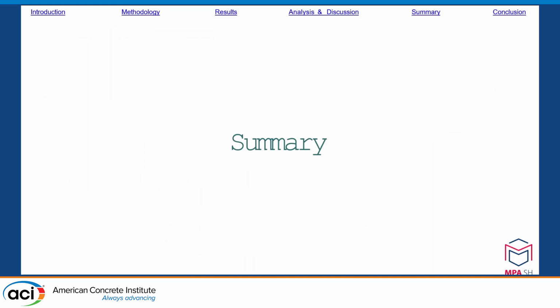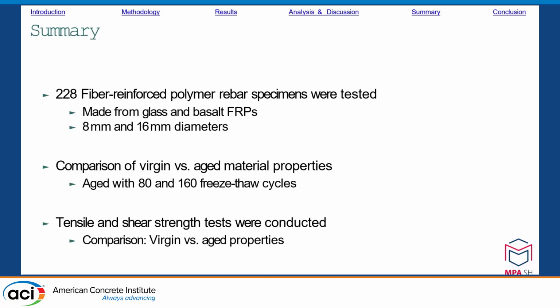In conclusion, I will briefly summarize my presentation. A number of 228 fiber-reinforced polymer rebars made of glass and basalt with 2 different diameters, namely 8 and 16 millimeters, were tested. Some of the rods were aged through 80 and 160 freeze-thaw cycles. Tensile and shear strength tests were carried out to compare the frost-aged and virgin bars.